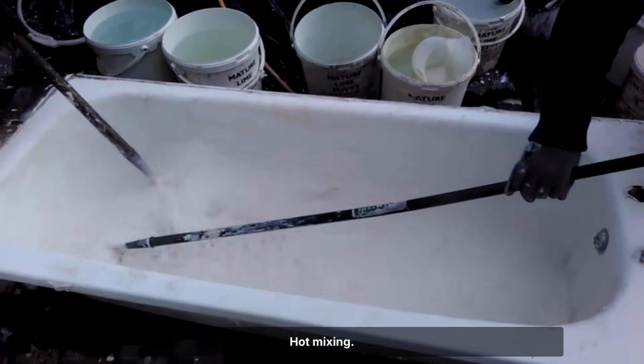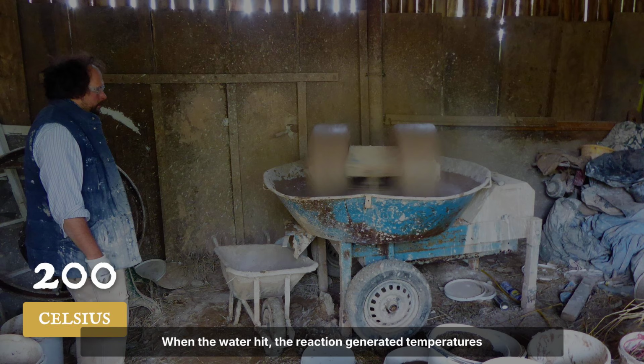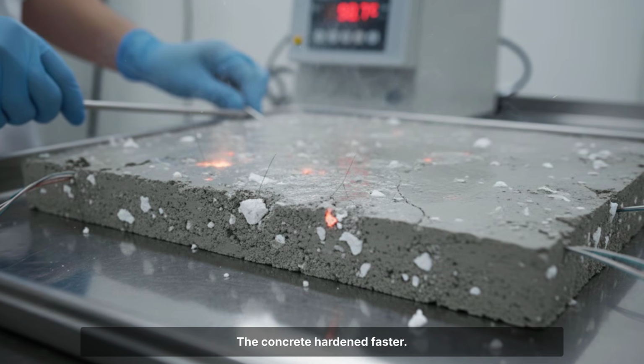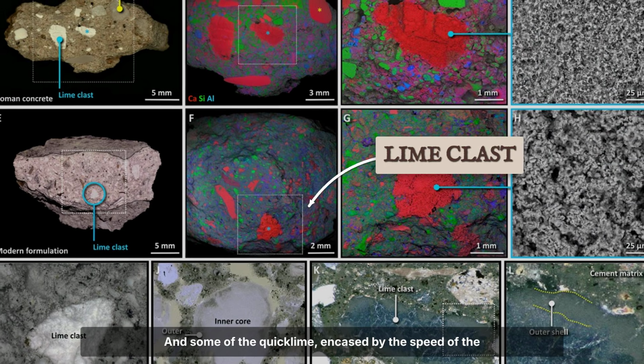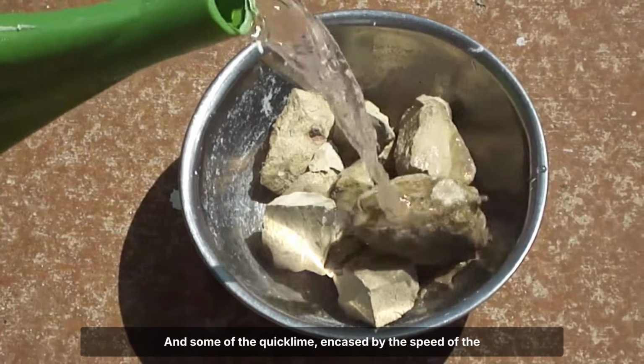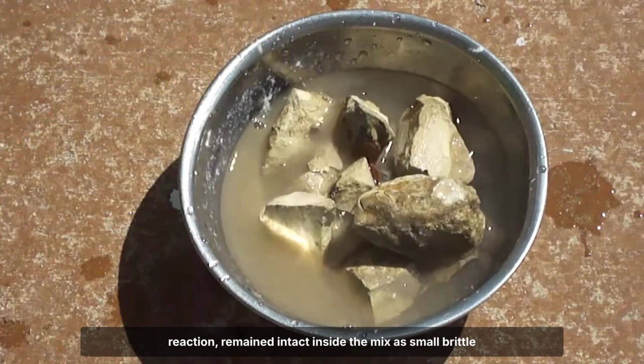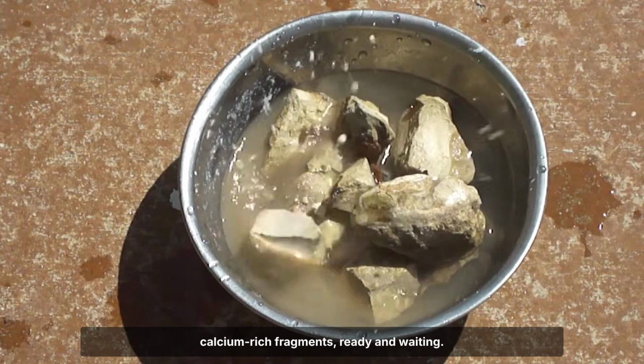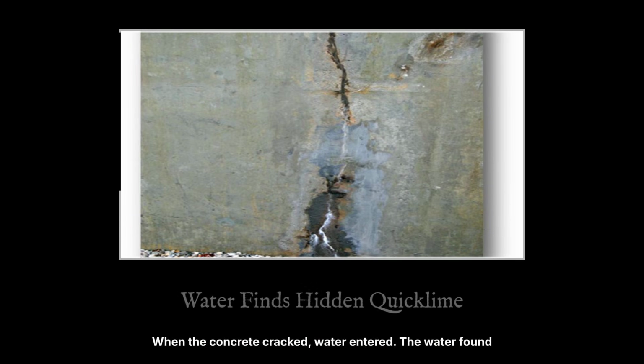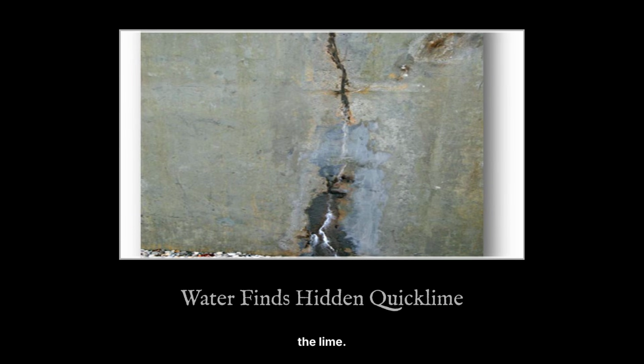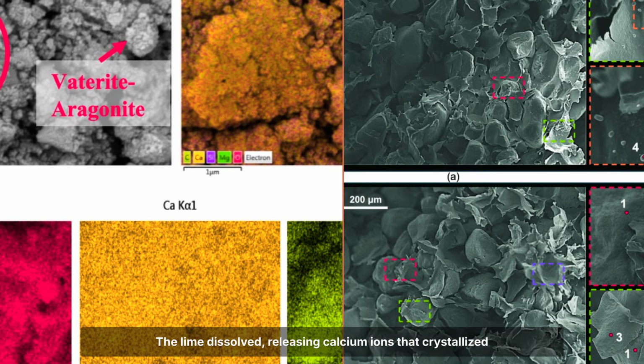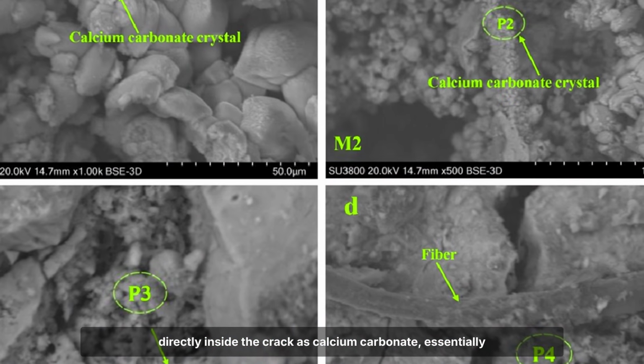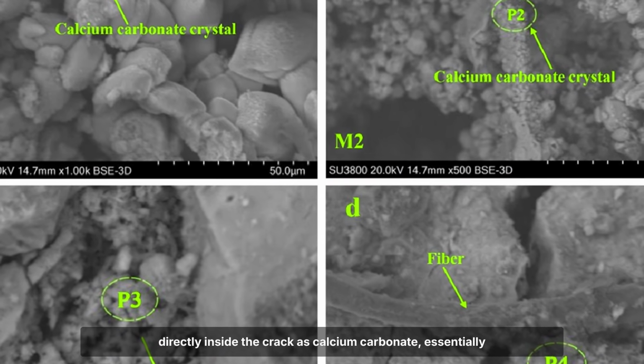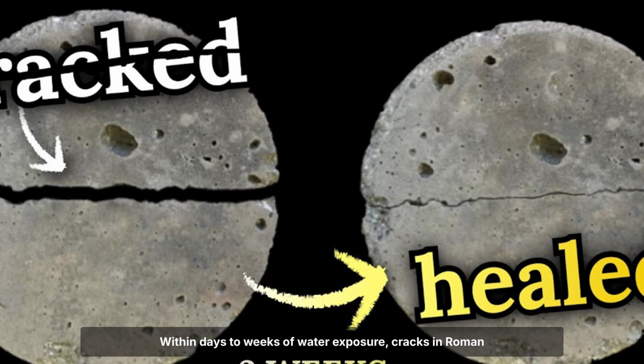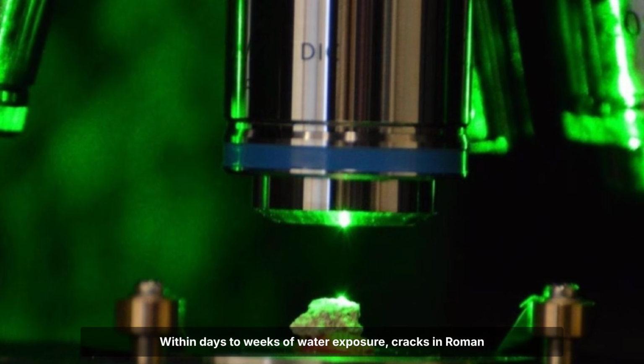water. Hot mixing. When the water hit, the reaction generated temperatures exceeding 200 degrees Celsius at the hotspots. The concrete hardened faster, and some of the quicklime, encased by the speed of the reaction, remained intact inside the mix as small, brittle, calcium-rich fragments, ready and waiting. When the concrete cracked, water entered. The water found the lime. The lime dissolved, releasing calcium ions that crystallized directly inside the crack as calcium carbonate, essentially limestone. Within days to weeks of water exposure, cracks in Roman concrete sealed themselves shut.